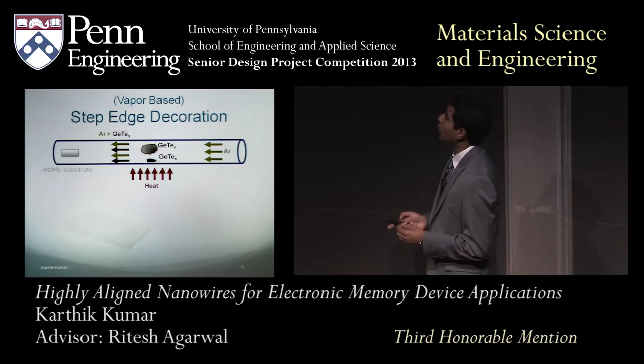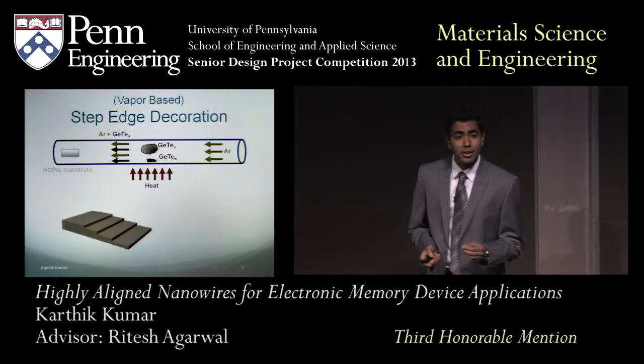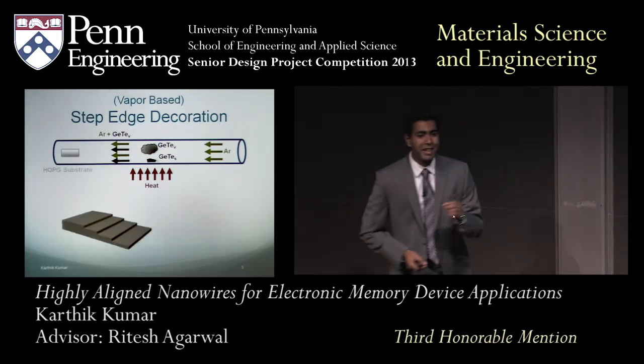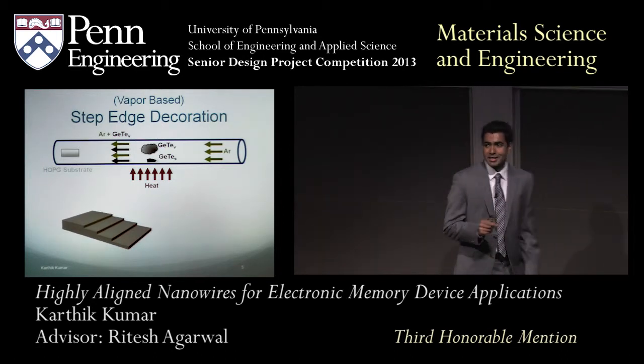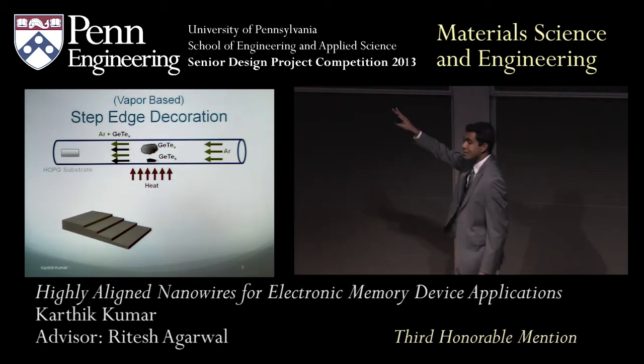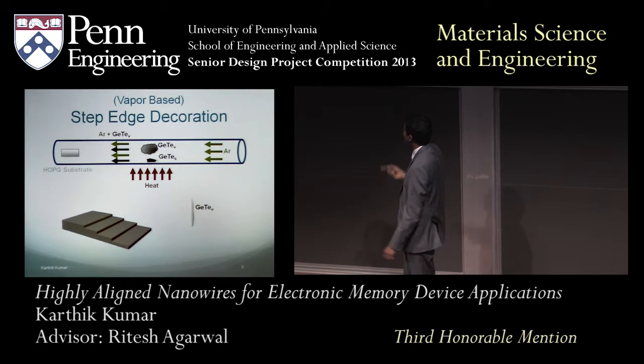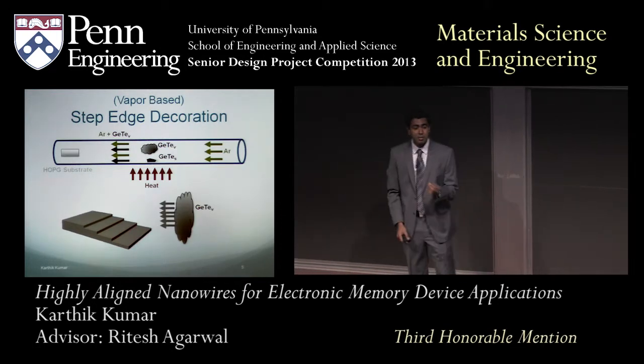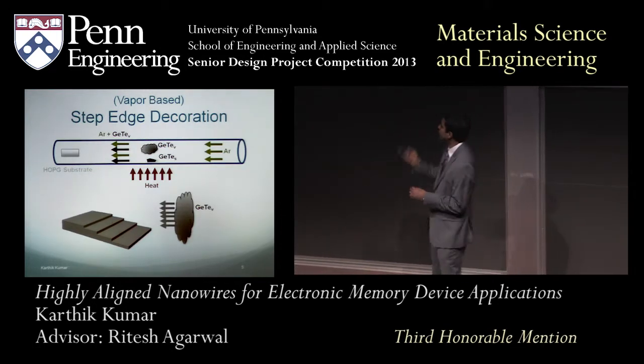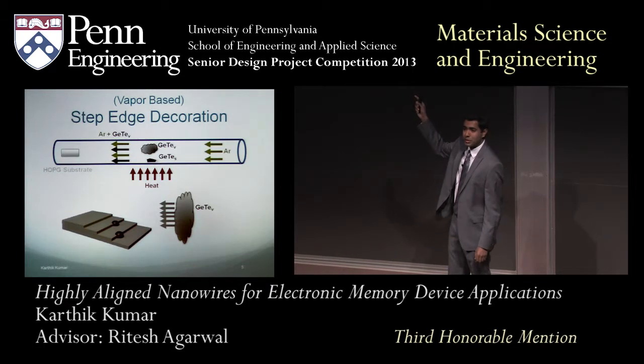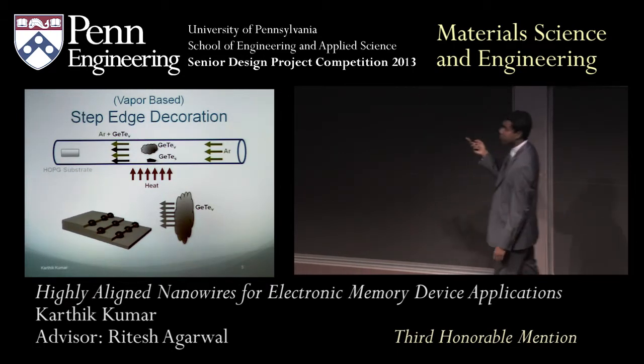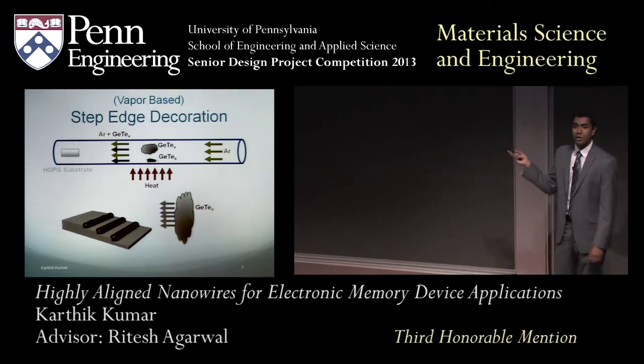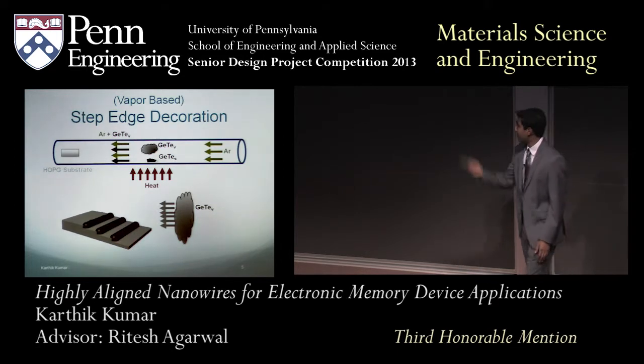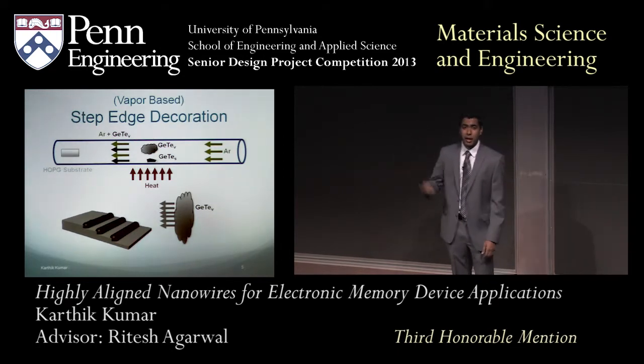There it sees what's called a highly oriented pyrolytic graphite substrate. Now that's a mouthful, but what that means is at the atomic level, it has these little step edges. And when incident upon with the vapor, these steps act as little nucleation sites for the GeTe to precipitate out. And over time, we form more nuclei until they coalesce and form continuous nanowires. And these happen to have the property that they're parallel.